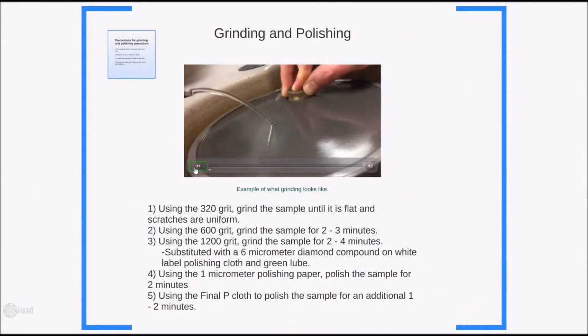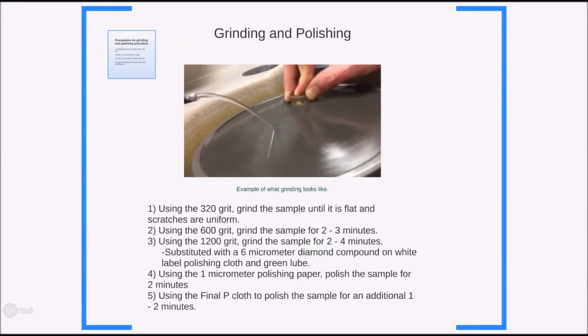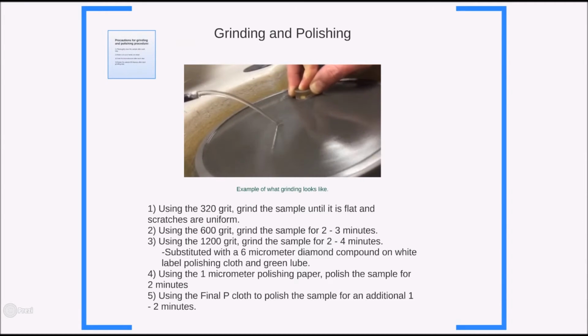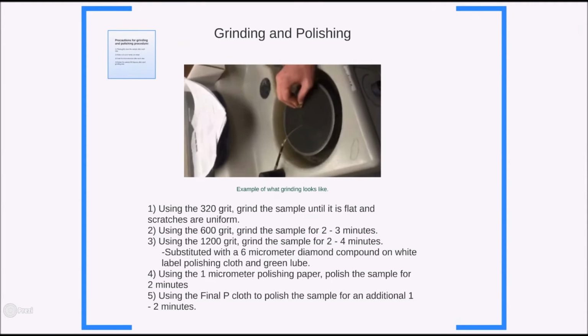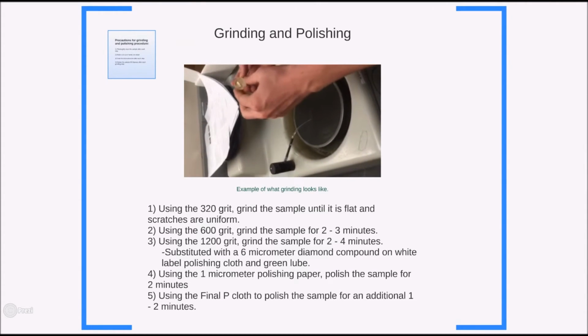Grinding and polishing. Using the 320 grit, grind the sample until it is flat and scratches are uniform. Using the 600 grit, follow the procedure in step 1 and grind the sample for 2 to 3 minutes. Using the 1200 grit, follow the procedure in step 1 and grind the sample for 2 to 4 minutes. Step 3 can be substituted with a 6 micrometer diamond compound on white label polishing cloth and green lube.